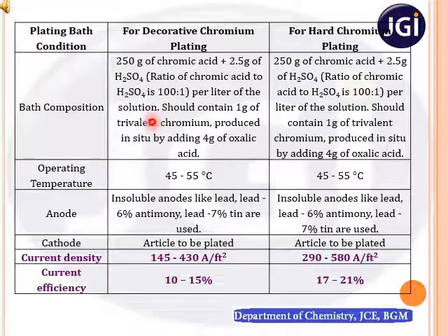Apart from this, the electrolytic bath should contain 1 gram of trivalent chromium, which is produced in the electrolytic bath itself by adding 4 grams of oxalic acid, so that we can always maintain 1 gram of trivalent chromium, which is essentially required for uniform coating of chromium to the substrate. The bath composition is the same for decorative as well as hard chromium.